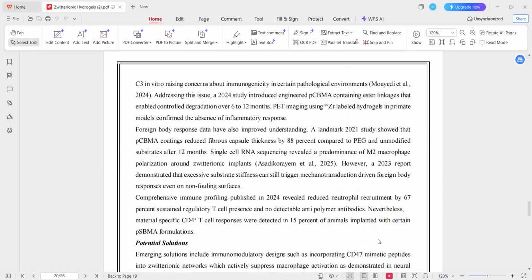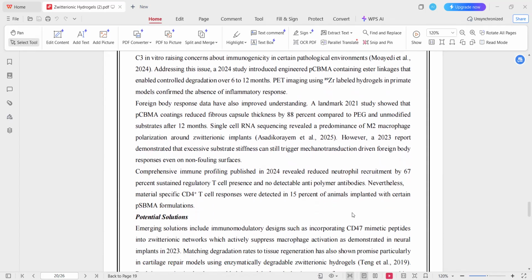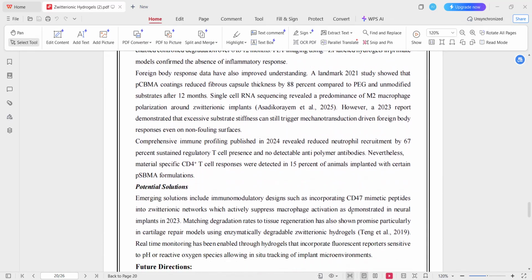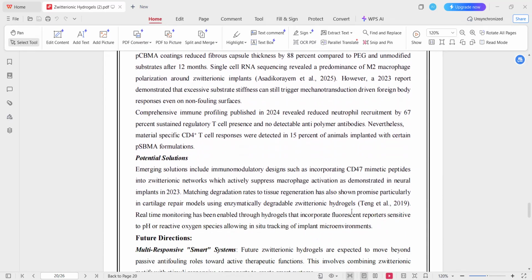Foreign body response studies further demonstrated that carboxybetaine methacrylate coating reduces fibrous capsule thickness by 88% compared to PEG after 12 months, and immune profiling revealed reduced neutrophil recruitment and a dominance of healing-associated M2 macrophages. A 2024 study on zwitterionic hydrogel showed that these materials are generally well tolerated by the immune system. They reduce neutrophil recruitment by 67%, maintained regulatory T cell presence, and did not trigger detectable antipolymer antibodies. However, CD4 plus T cell responses were observed in 15% of the animals implanted with certain sulfobetaine methacrylate formulations.